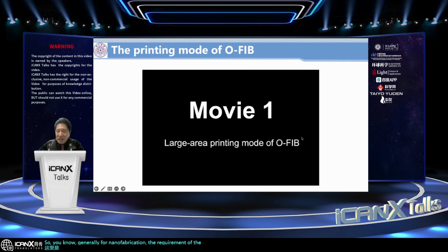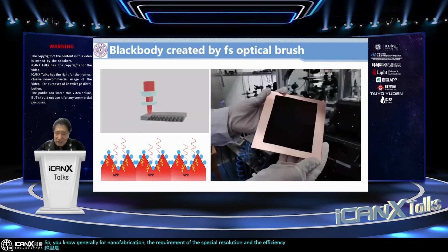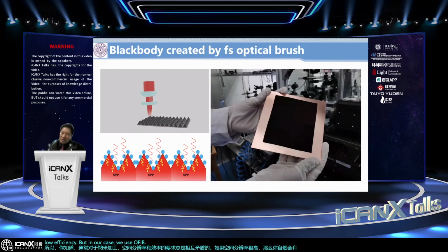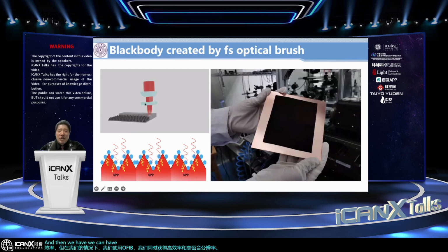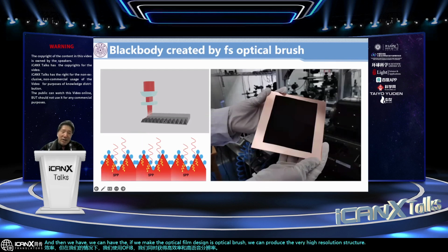Generally for nanofabrication, the requirements of spatial resolution and efficiency always contradict each other. If the spatial resolution is high, then naturally you have low efficiency. But in our case, we use the OFIB, and we get both simultaneously, high efficiency and high spatial resolution. If we make the femtosecond laser optical brush, we can produce very high spatial resolution structures with very high efficiency.